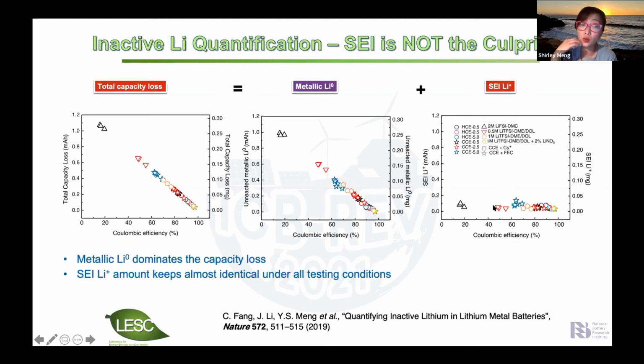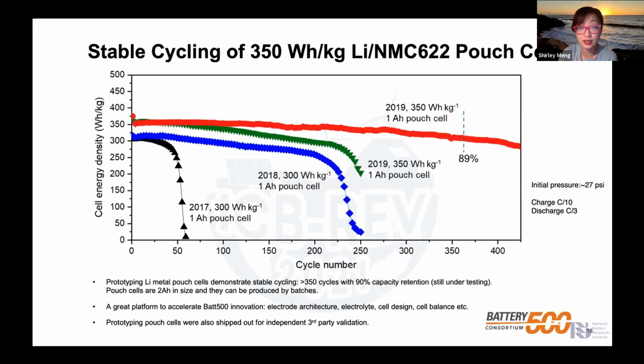So with this work, we clarify the previous misunderstanding in the field that in the low Coulombic efficiency batteries, SEI is the major culprit. In fact, the SEI amount stays almost identical in all test conditions, and we emphasize the importance of microstructure control for lithium metal batteries. And as we are part of the Battery 500, I just want to say that today the lithium metal batteries made by Pacific Northwest National Lab can actually cycle so much better than when we first started the project, with very promising energy density and cycle life.